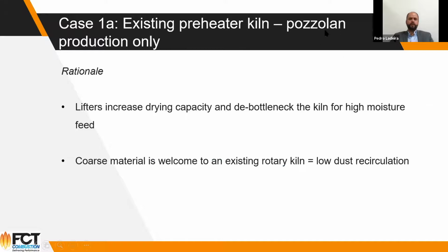So if we go for only pozzolan, the rationale here is that we can install lifters, and by installing lifters, we increase the drying capacity, and we probably debottleneck the kiln for high moisture feed. So whenever the feed is high, you have to have a very huge drying section on the kiln, so it may bottleneck the kiln capacity.